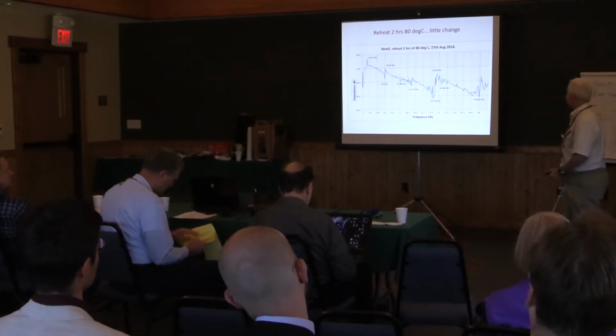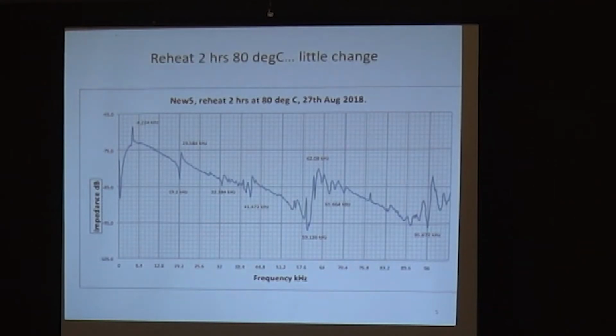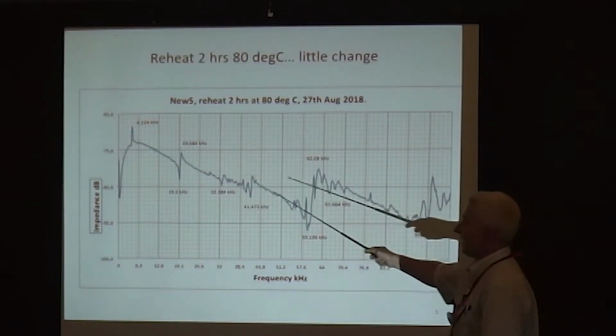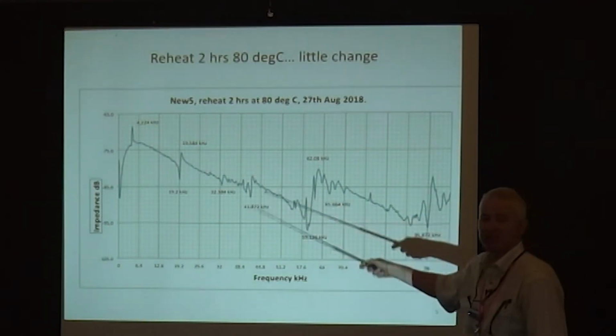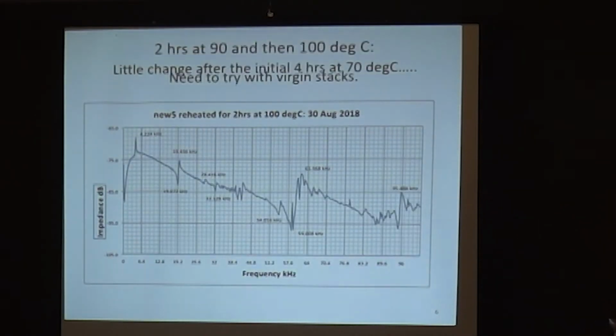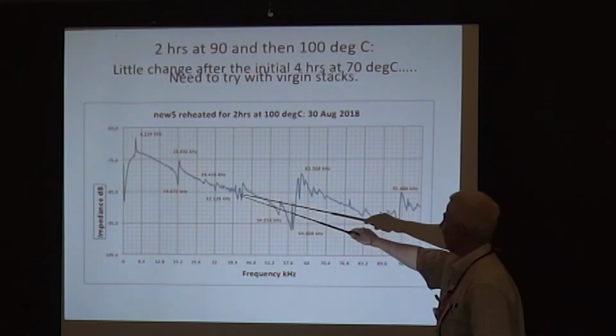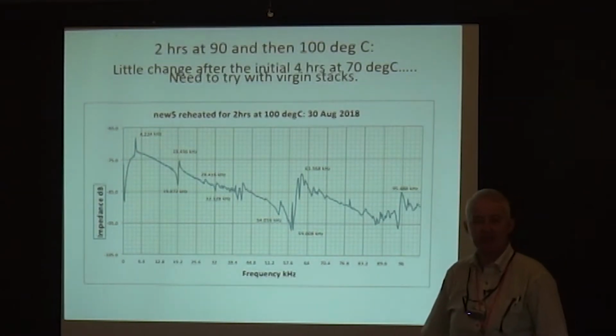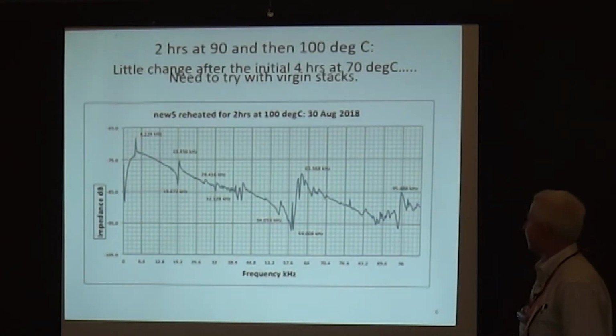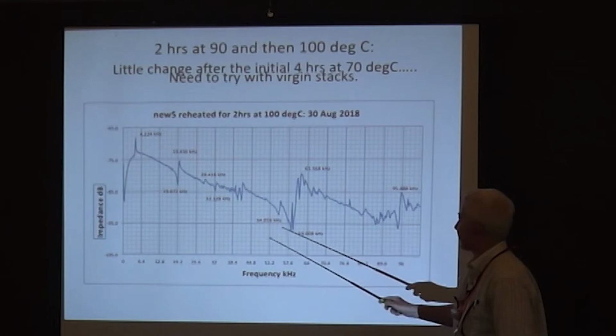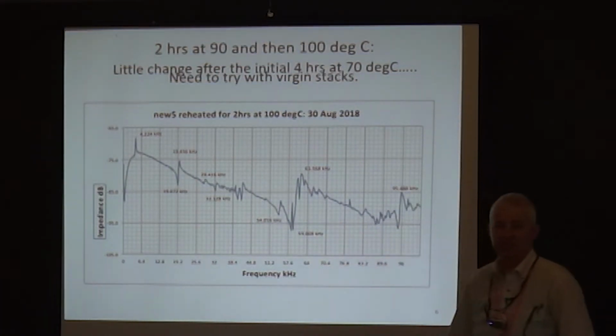So thank you. So here's a reheat at 80, and we didn't see really any change from the reheat after 4 hours at 70. It really didn't do anything new after that. And again, I reheated it at 100 degrees C. Again, really nothing is changing after that 4 hours at 70 degrees C. This is all looking pretty much the same. Maybe a little shift here, but very little happened.